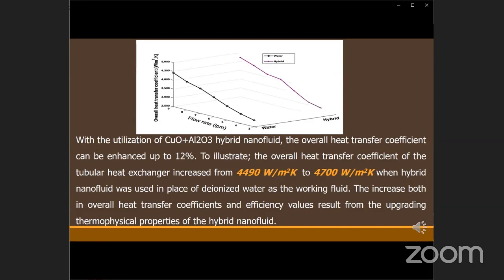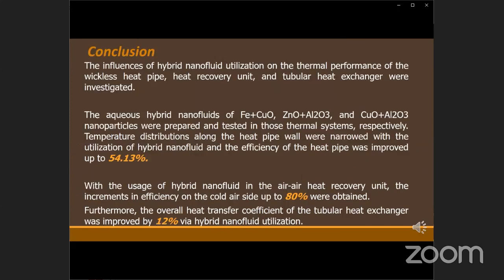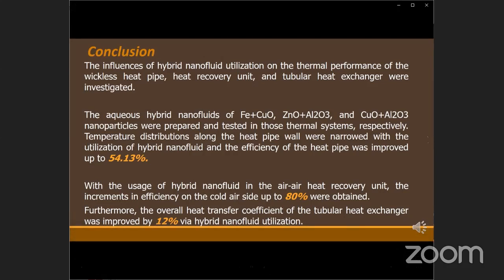The increase both in overall heat transfer coefficients and efficiency values result from the upgrading thermophysical properties of the hybrid nanofluid. To sum up briefly, the influences of hybrid nanofluid utilization on the thermal performance of the wickless heat pipe, heat recovery unit, and the tubular heat exchanger were investigated. The aqueous hybrid nanofluids of iron copper oxide, zinc oxide alumina, and copper oxide alumina nanoparticles were prepared and tested in those thermal systems respectively.